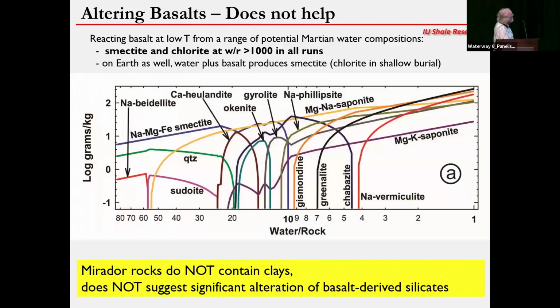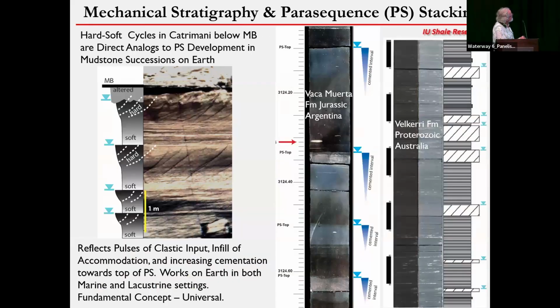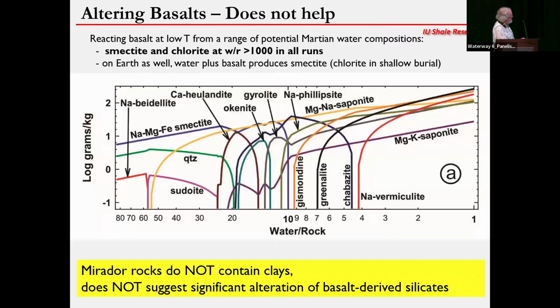So next. Now, some people have said, oh, you can't see the sand grains anymore because they've been altered to bits by post-depositional alteration. The only problem with that is that if you react a basalt at low temperature in a range of potential Martian water compositions, we tried quite a few of them, it's always a lot of smectite, some chlorite in all runs. So it's basically you form clays. There's no escaping from it.